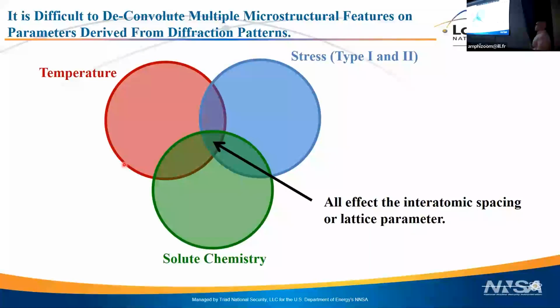So if we look at what's contained in a diffraction pattern, for this interatomic spacing, which you get from the position of the lattice parameter, or the position of the peaks, there are at least 3 things that are relevant to material science included in that peak position. Temperature, of course, affects the interatomic spacing. Stress affects the interatomic spacing, and you have to break stress down even further.